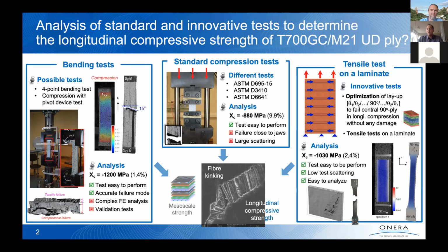My last comment concerning the compression test is really dedicated to the question of whether it is a material strength or not. You can see that the strength associated to the bending is higher than that measured considering an in-plane loading. And it is found in the literature also for many other carbon epoxy materials, because the fiber kinking is really associated to fiber microbuckling, which is not a material mechanism but, as it has been mentioned previously, an instability phenomenon. So we have to think about the choice of the scale we are going to consider for the modeling and for the analysis of the mechanism, especially for compressive loading. Thank you for your attention.